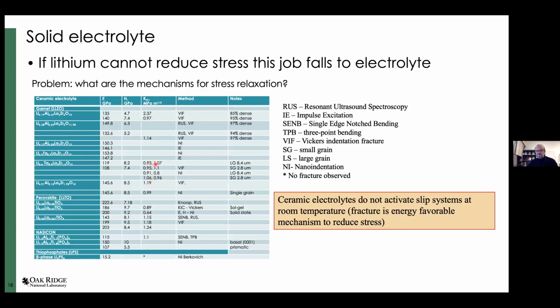Ceramics are brittle. This table compiles values of fracture toughness obtained by different methods, and we need to be really, really careful how we compare them, because fracture toughness obtained from single edge notch bending represents the strength of many grains. It's really a bulk measure, and fracture toughness obtained from nanoindentation is a totally different measure.